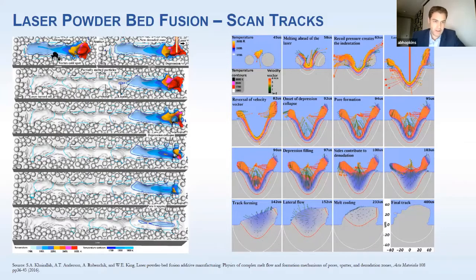So what you're doing is, as you move the laser away, this is a lower density, extremely hot melt that's at vaporization or close to it, some parts of the melt pool. And as it cools, you have Marangoni convection. So the lower density, cooling metal pulls the metal from the hot spot backwards, if you will, in the opposite direction of the scan track. And that's what fills in the gap.